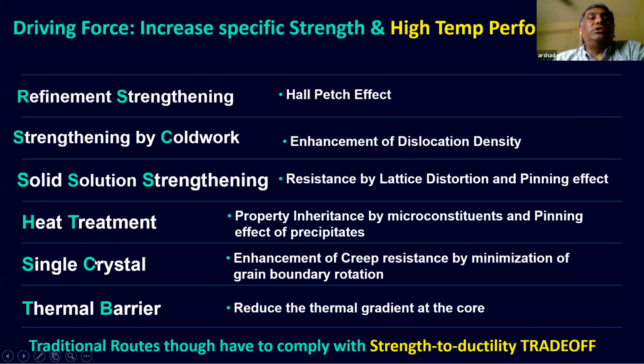That is why, in the case of engine materials, the main objective is not refinement but having a single crystal, so that grain boundary slip is minimized and creep resistance can be enhanced. If creep resistance is enhanced, the material will deform less, and it can work under tighter clearances. So single crystal casting is used for engine materials, and later advancements in superalloys are coated with thermal barrier coating to reduce the temperature gradient inside the turbine blades.